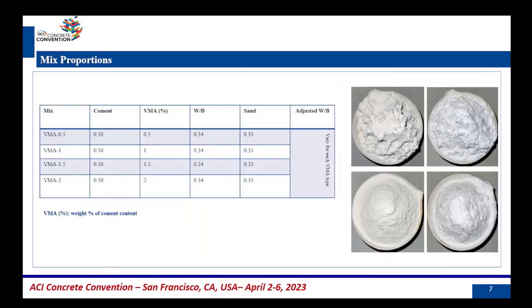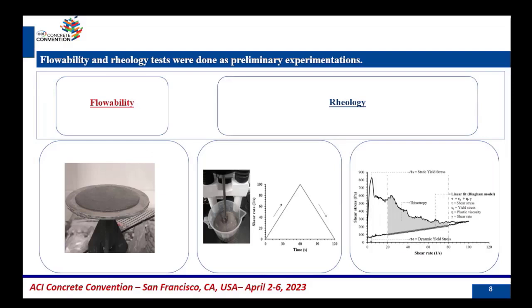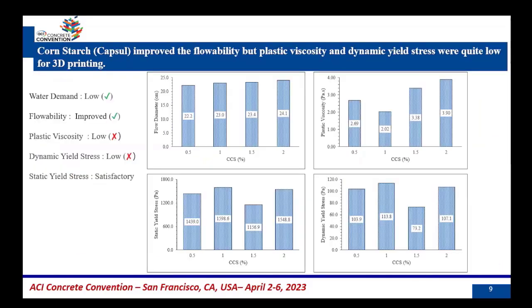This is the generalized mixed composition of different viscosity modifiers. So we use viscosity modifier in different proportions as percentage weight of cement, starting from 0.5, 1, 1.5, and 2%. For the initial testing, we did flowability test and rheology testing. We used Brookfield's rheometer,